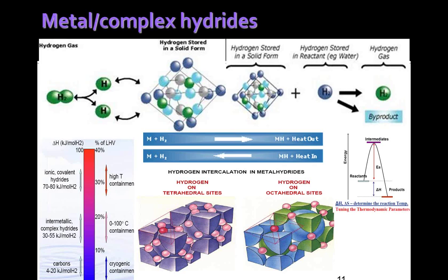It's more like a cryogenic temperature. Then the carbon materials, like carbon nanotubes, single-wall nanotubes, multi-wall nanotubes, their energy or delta H is about 4 to 20 kilojoules per mole hydrogen. So that is about 10% of LHV.